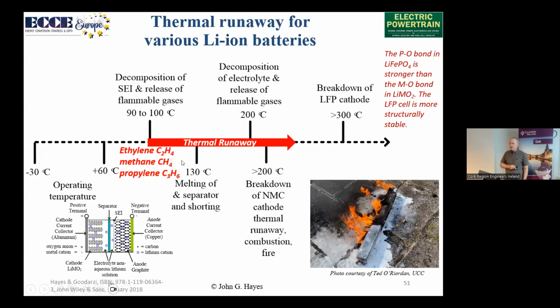One of the things here is, as the exothermic reaction goes into thermal runaway, everything is going to heat up. We're going to start melting the separator. And once we melt the separator, which is a polyolefin, which is also a hydrocarbon, we are going to get shorting from anode to cathode. So exothermic temperature is building up.